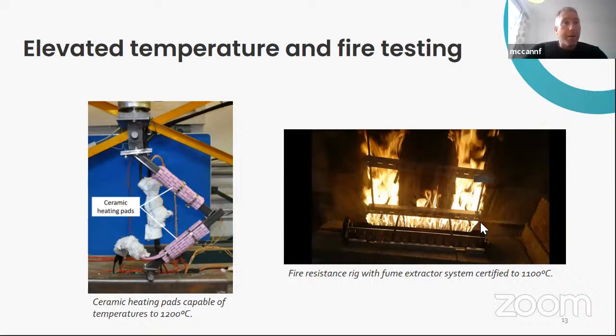So we've got some ceramic heating pads that can heat up to 1200 degrees C. So this is some testing we did on high strength steel a couple of years back. And so that's the elevated temperature side of the testing. And on the right hand side here, we've installed and upgraded a fire resistance rig. So a propane based fire resistance rig. And we've recently upgraded our fume extractor system. So it's certified up to 1100 degrees C. So we're in the process of tuning this up to get it in line with BS 476, part 6 and 7 on flame propagation and surface spread.